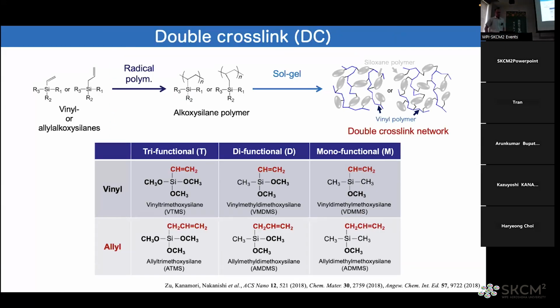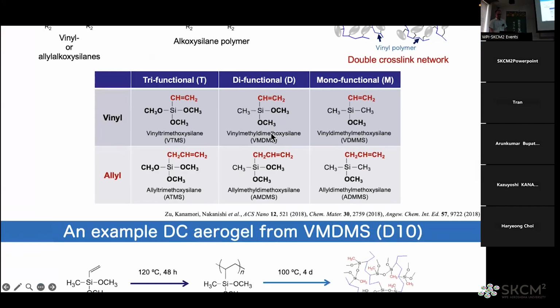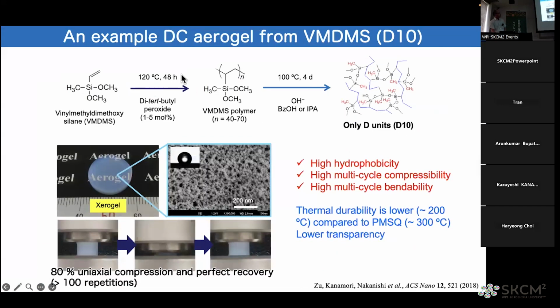So now we know that hydrocarbon chains, not only siloxane networks, also work for better mechanical property. So we did it the opposite way. First, we polymerized the vinyl groups to have the hydrocarbon chain, and then reacted hydrolysis and polycondensation to form the polysiloxane network. Then the process is like this, polymerization and hydrolysis and polycondensation in a solvent. Then we can prepare the translucent aerogel like this.